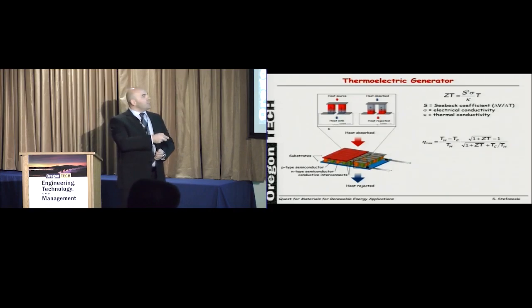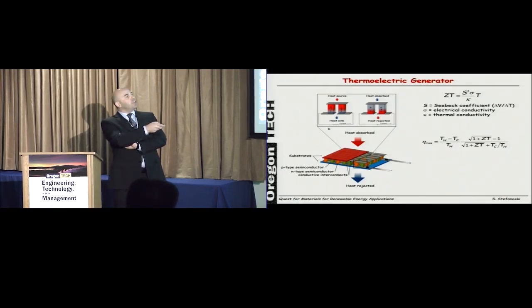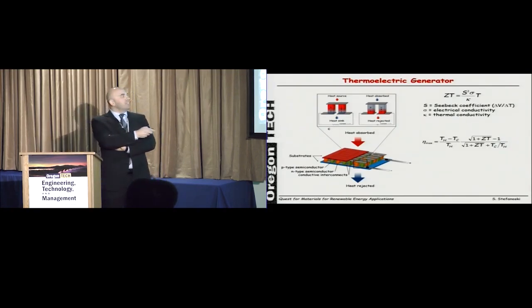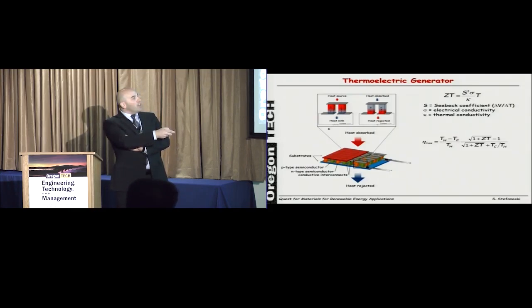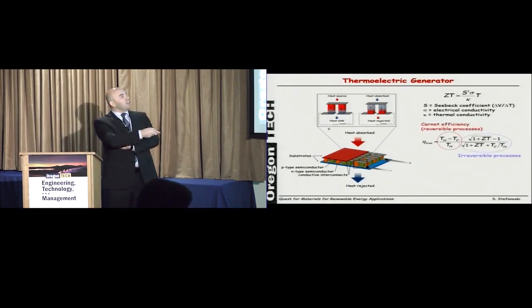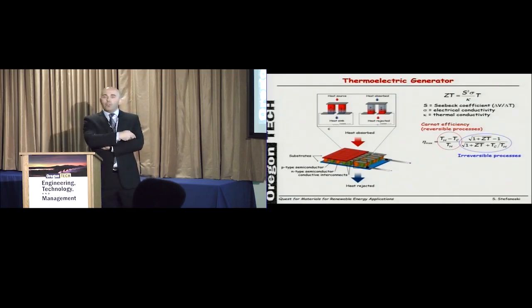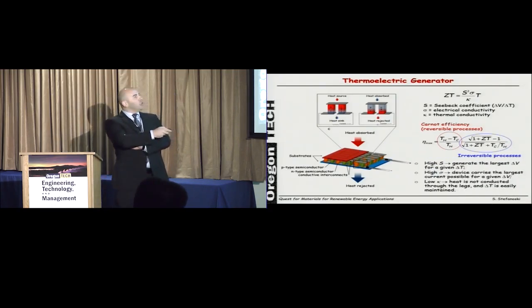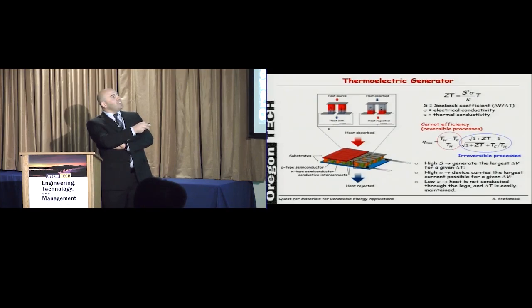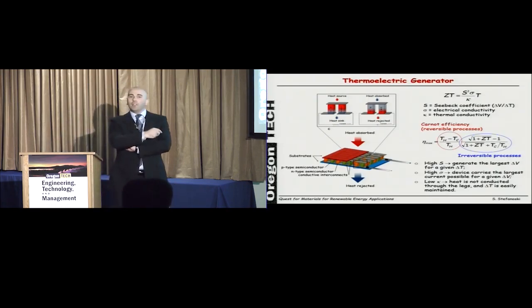The efficiency of this thermoelectric generator is assessed via the dimensionless figure of merit called ZT, which depends on the Seebeck coefficient, the electrical conductivity, and the thermal conductivity. The introduction of temperature is only to make this parameter dimensionless. And the efficiency of the thermoelectric generator depends on that ZT. The higher the ZT is, the higher the efficiency is. Here we can notice that this is just the Carnot efficiency and this is a result of irreversible processes, but the common conclusion is that if we need a high ZT value and high efficiency in thermal to electrical conversion, we